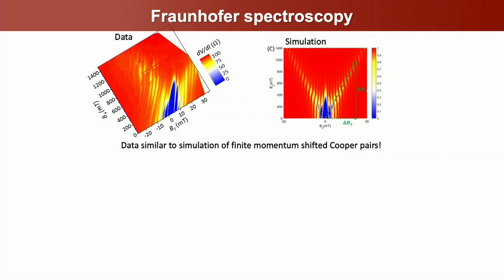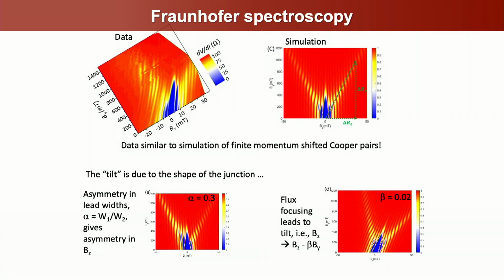And again, what you see here are your Fraunhofer patterns. If you make a slice through here, you'll just see the expected Fraunhofer patterns of that single slit pattern. But now you can see the single slit pattern is lifted to higher values of BZ, basically in this trident shape, very much like what we expect. We can show that this tilt is just due to the shape of the junction, both due to the asymmetry of the leads because of the shape of our bismuth selenide and due to a flux focusing effect.